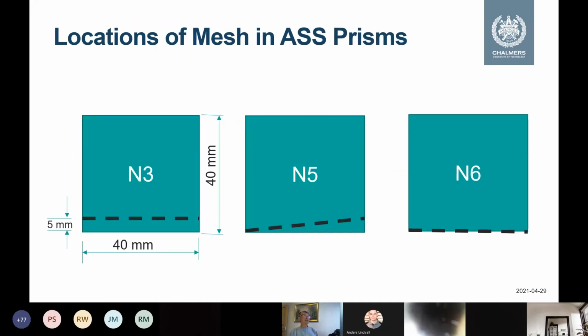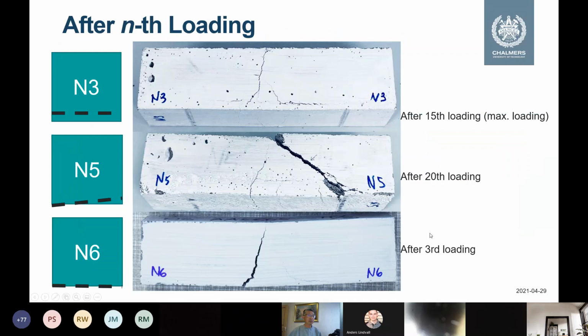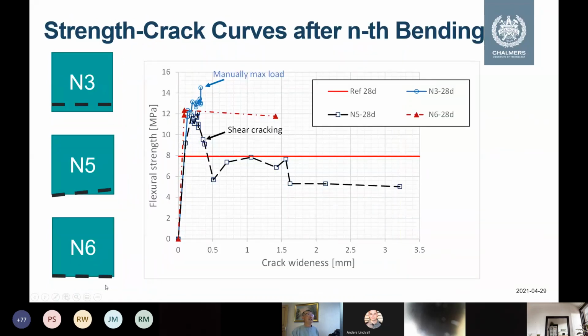And then we also tested this mesh in alkali-activated prisms. With different positions, we have completely embedded, half embedded, and not embedded. Here are the results. This is completely embedded, after 15 loadings with maximum load. There is no damage, we cannot damage it. After the 20th loading, it becomes a shear failure, a shear crack. Of course this one breaks because the fiber is outside.